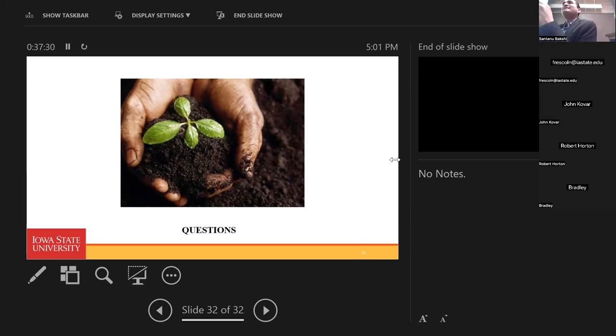So we are considering just electrostatic adsorption. We are considering the corn stover, iron biochar, and zeolite. The rest of the ammonium can be adsorbed onto the zeolite. So yes, we have tested before low ash biochar for phosphate and high ash biochar for nitrogen, but we found that the best way to go is the one I described.